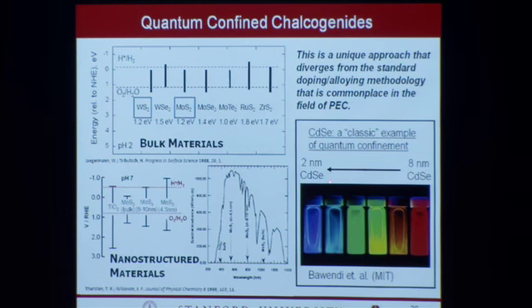And here's an example of the quantum confinement effect. This is with a different chalcogenide, cadmium selenide. There are a number of images like this that you can find because it's a classic case where the cadmium selenide, as I mentioned before, has a band gap of 1.7 eV in the bulk. That means that when you shine UV light, it will fluoresce out photons at 1.7 eV, which is red light. And as you make them smaller and smaller down to 2 nanometers, you get quantum confinement, and you can widen the band gap up to about 2.8 eV. So this is the effect that we're taking advantage of.